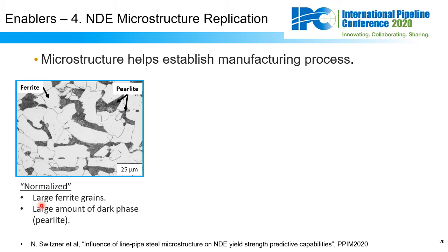And important features in the microstructure are, one, the grain size, which is the size of these light areas called ferrite, two, the fraction of these dark areas or lamellar areas called pearlite, and three, the shape of these areas, called morphology. So here we have a normalized microstructure which is characteristic of a lot of vintage steels, and it's evident of older or low-grade pipeline steels with these large ferrite grains and large amounts of this dark phase called pearlite.